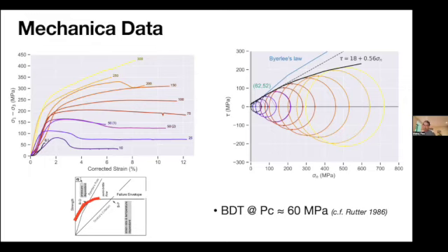And if we go back to this plot that I was explaining earlier, then we're basically exploring in these experiments this range where we go from the fracturing envelope towards the semi-brittle flow field, and our differential stresses at 300 MPa are still higher than the confining pressure, so we don't reach entirely the brittle plastic transition. So